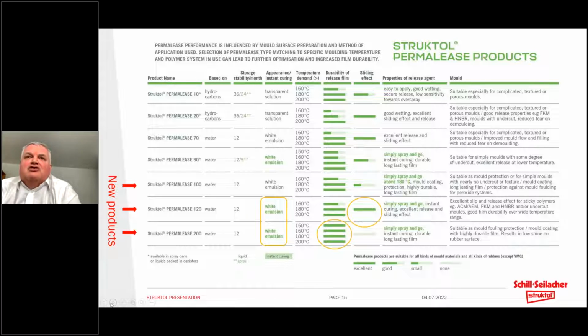We must, however, compare, or if you like, contrast that against the sliding effect. Some mold release systems really are needed to provide a release for very sticky compounds, or for those molds where we have complex geometries and undercuts, where we really need a slippery or sliding, gliding surface in order to provide release. And quite often, the harder, more durable coatings don't provide that degree of slippiness. And we can see that, for example, with our Permalease 200. Very durable coating, but not so much of a sliding effect. Other coatings can really be optimized to maximize the sliding effect by changing one of the polymers within the system to provide a more flexible and slippery polymer. We can really aim to optimize both the durability or provide a very high degree of release and sliding effect for those more complex geometries or sticky compounds.